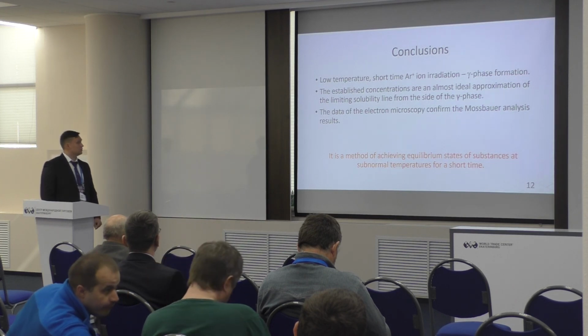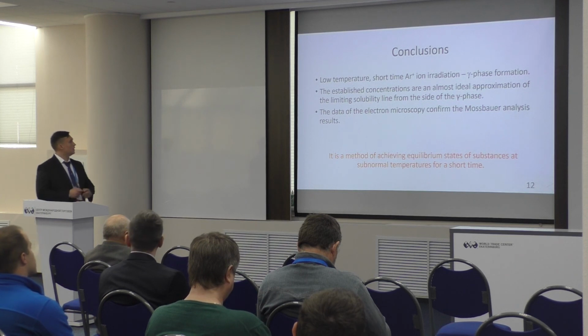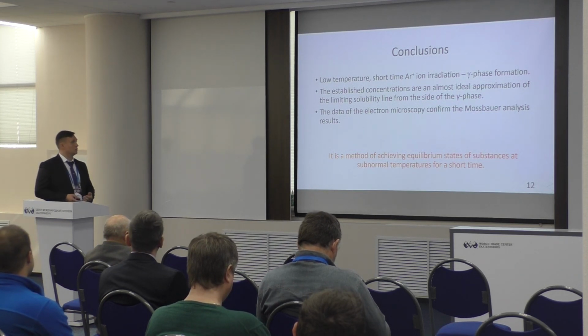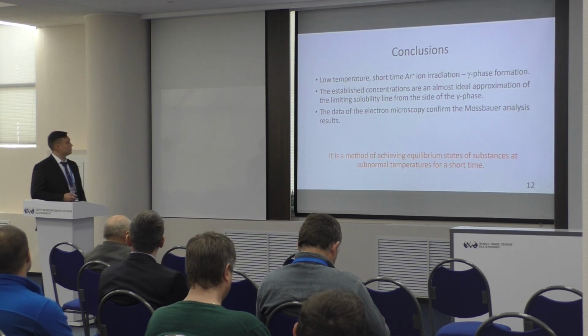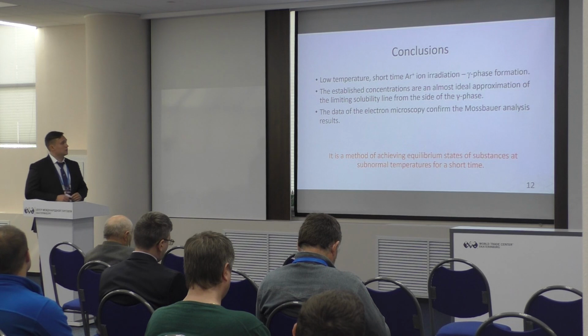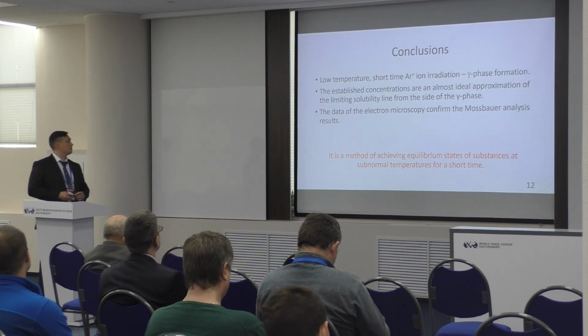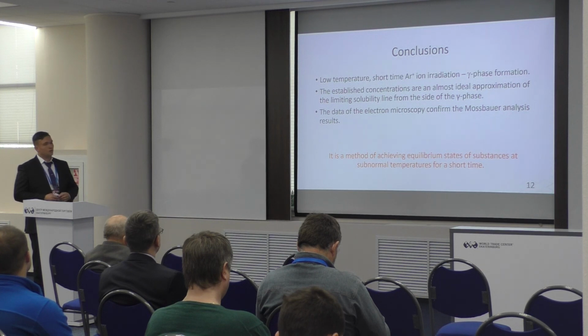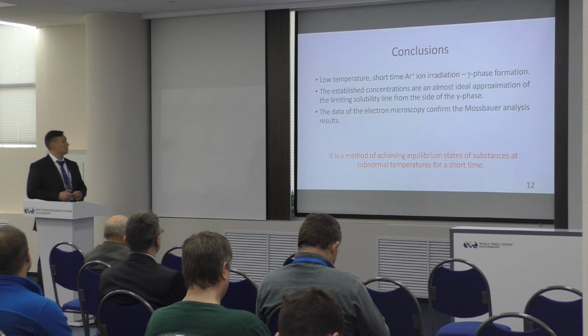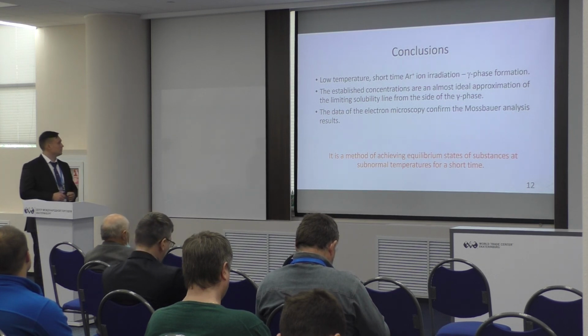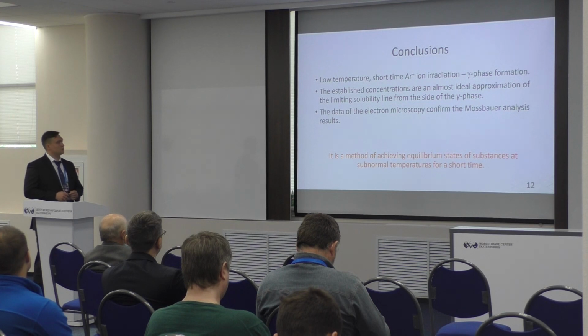In conclusion, I'd like to say that we used ion irradiation to get the gamma phase to form in our alloy, and it was low temperature and short time ion irradiation. Also, we constructed the low temperature area of the iron-manganese phase diagram, and we confirmed our Mössbauer analysis results using electron microscopy. And this method is a good method for achieving equilibrium states of alloys at subnormal temperatures for a short time.